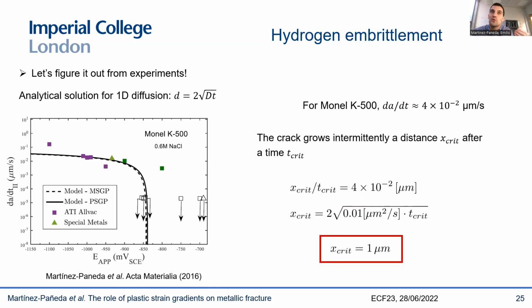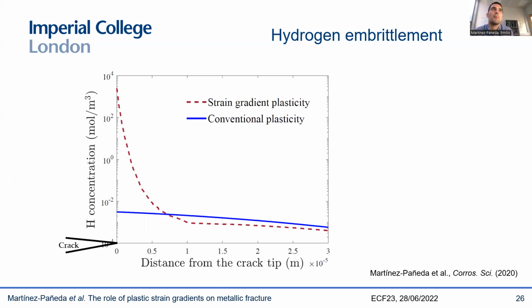So at 1 micron, as we saw before, gradients play a big role, and we therefore need to account for GNDs if we want to tackle this hydrogen embrittlement problem. And you can see here that if you plot the hydrogen concentration ahead of a crack, as you would expect from the previous results, in conventional plasticity you are under-predicting very significantly the hydrogen concentration ahead of your crack tip compared to gradient plasticity.